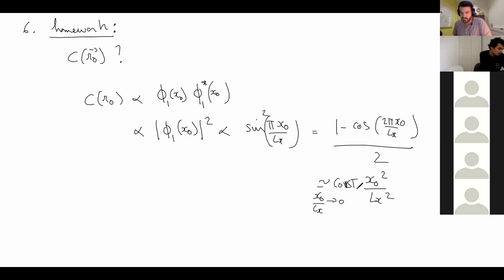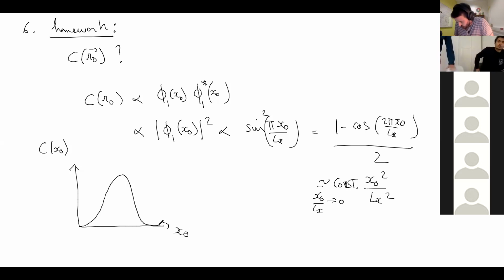Okay, so what it means is that if you are now in your box and you're plotting the concentration, you should end up with some cosine shape. So it's more like a Gaussian, but it's a cosine. This is Lx, this is 0. And this is the bulk reference. Well, what the presence of the wall generates is an overpopulation at the center of the box and a depletion at the boundaries, at the borders, due to the fact that all the conformations are in fact folded. Since you cannot go outside, you have to fold back, and so it depletes the region near the wall. Okay, and so it seems that if you are now able to look at the statistics of probability of your monomers inside the box, you will see fewer monomers near the walls than at the center, and there is no repulsion force. It's purely entropic.